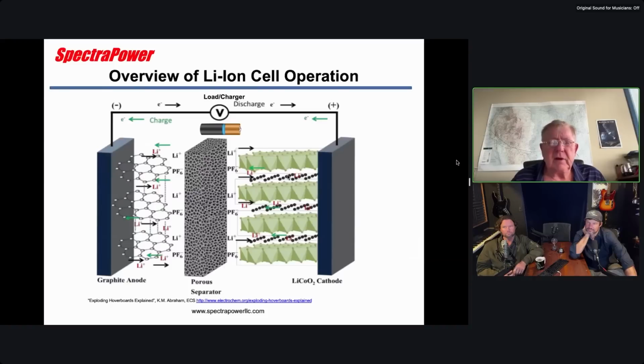The other thing, by the way, is if you pull this charge out too fast and you try to charge the cell too quickly, you can cause a problem, because this intercalation process is a physical process. If you remember pencil lead from school, it's kind of flaky, right? I don't know if you ever played with graphite. And it's those planes that the lithium's going into. And so the morphology, in other words, the shape and structure of the particles, is important, especially on the anode here.